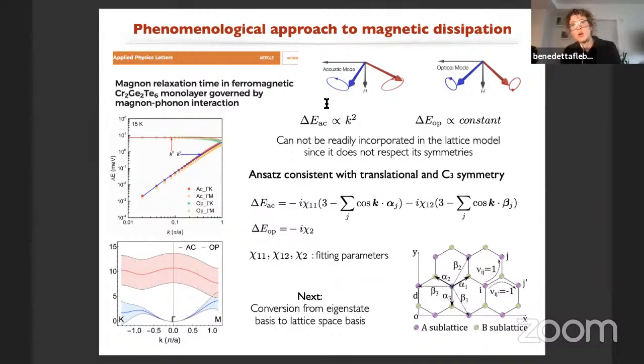In a honeycomb lattice, you will have two sublattices, therefore ultimately two eigenmodes: some acoustic mode that is an in-phase mode, and some optical mode at higher energy, which is out of phase. Here, this broadening turned out to scale as k squared, and this one, from their simulation, is a constant. So this cannot be readily incorporated in our lattice model. It does not respect our translational and C3 symmetry. So we make this ansatz for the broadening.